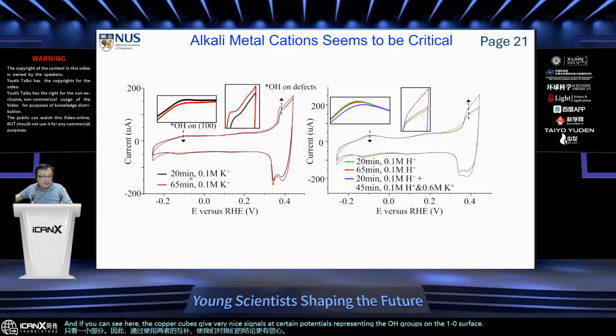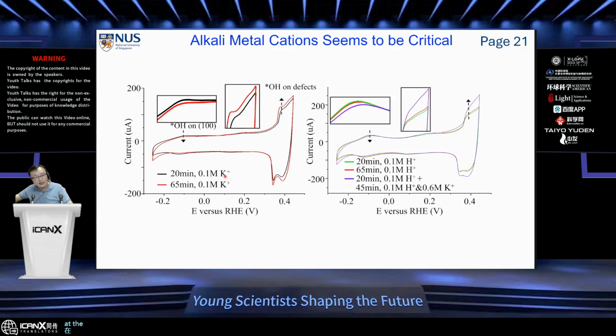And you can see that if you just do a 20 minute reaction within the electrolyte at -1 volt with potassium cation in the electrolyte, that serves as our baseline. So we assume that within 20 minutes, the surface oxide will be removed entirely. Then if you extend the reaction to 65 minutes, any additional change that we observe will not be related to the oxide reduction. It will be something else. And we did observe a very significant change. See the red curve and the black curve, so it's very different. And this is consistent with our microscopy observation.